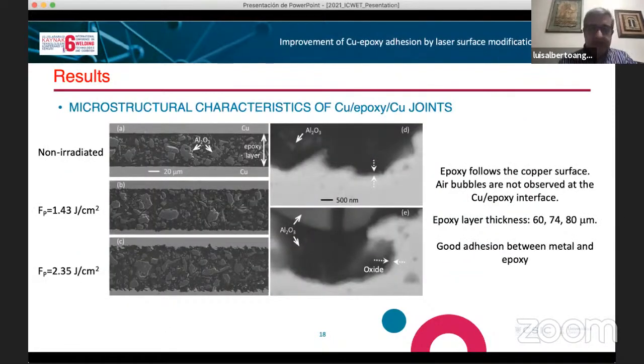Also, you can check the aspect of the joint. Here we have fabricated joints between two copper plates, and after characterization, we have prepared them to see the cross section in the scanning electron microscopy. You can see the aspect of the non-irradiated polished samples, and after the two-line scanning treatments, with the lowest fluence and with the highest one.